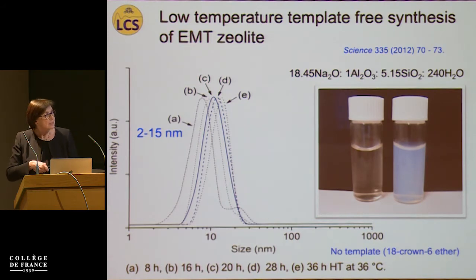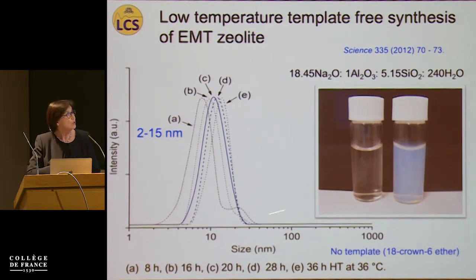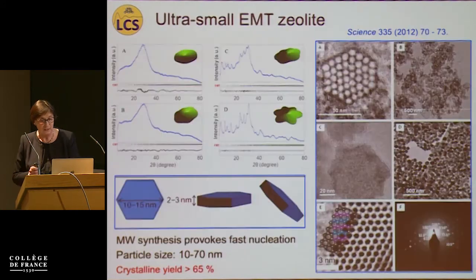And this is the first example, how 18-crown-6 ether, classically used for synthesis of EMT-type zeolite, was replaced with sodium hydroxide. The key point here is to stabilize a water-clear precursor suspension, highly supersaturated, not with organic template, only with inorganic cations, and under very mild synthesis conditions, such as 36-degree heating for 36 hours, we have been able to transform this water-clear solution containing amorphous particles into EMT nanocrystals.